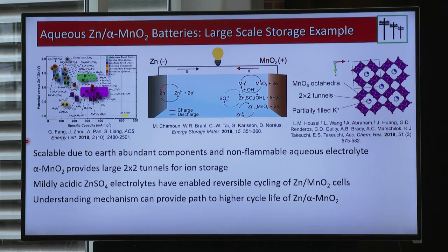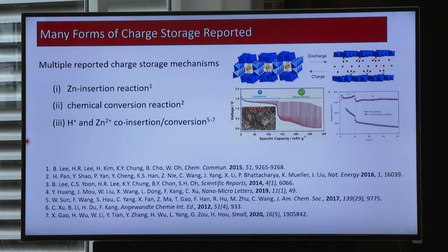And of course, as good researchers, we started off looking into the literature. And we were intrigued by this 2x2 tunnel because this 2x2 tunnel structure of manganese oxide, the tunnel is big enough to accommodate a zinc cation. But when we looked further in the literature, people have in fact tried to use zinc alpha manganese oxide for rechargeable batteries. But there are reports of many, many different types of reactions. Oh, zinc is inserting. Oh no, it's proton insertion. Oh, actually, manganese oxide is turning to something else. It's a chemical conversion reaction.